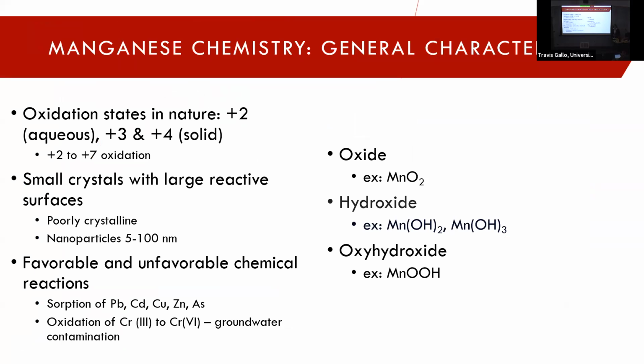In natural systems, manganese has the oxidation states of +2, +3, and +4. It also has the oxidation states possible of +2 to +7 in some non-natural systems. And that's more than any other transition metal. Because of this, it has the ability to gain or lose electrons while maintaining a solid phase. It's characterized as having small crystals with large reactive surfaces. However, it's poorly crystalline, and they're very small nanoparticles of around 5 to 100 nanometers in size.